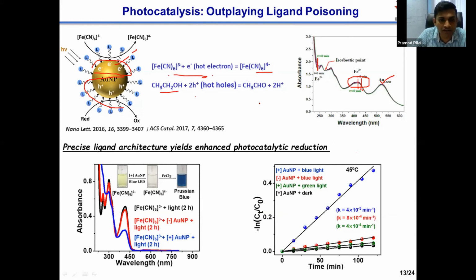So this is the summary of our results. When there is no catalyst, there is no reduction, and when there is a catalyst with an unfavorable surface chemistry, still the reduction is negligible. This is similar to what has been reported. But when we used our nanoparticle with favorable surface chemistry, we were able to see a drastic decrease in the peak of the reactant, along with the emergence of the peak corresponding to Fe2+. And we have also characterized this using the standard Prussian blue test. So the impact here is that with the favorable surface chemistry, we were able to see an appreciable catalysis which people were not able to observe.